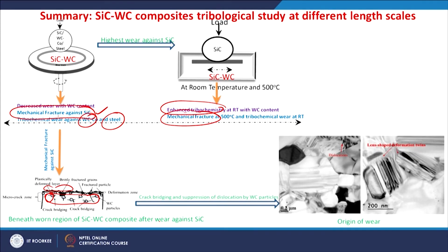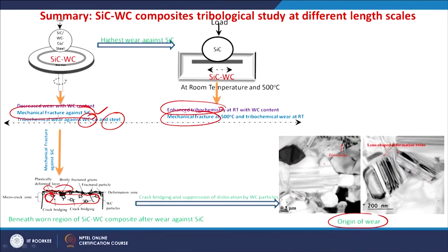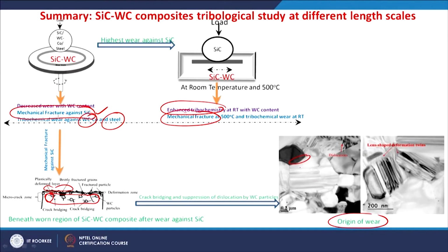Further analysis by TEM shows the origin of the wear occurs by the cracking. The cracking is possible by the stresses induced by the sliding at the tips of those deformation signatures like dislocations or the twins. So, these cracks will propagate further and lead to material removal. When a tungsten carbide particle is present at the interface, all these cracks are actually stopped, or the deformation signatures are not present at the interface or inside the tungsten carbide particles.